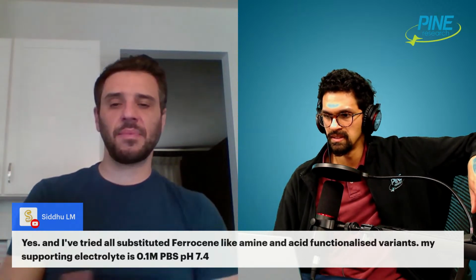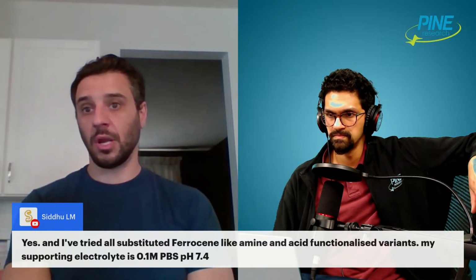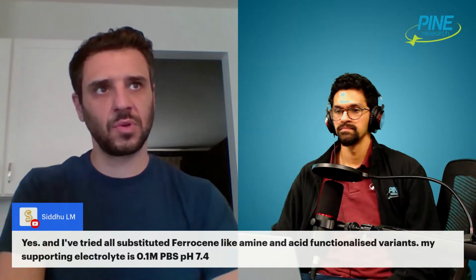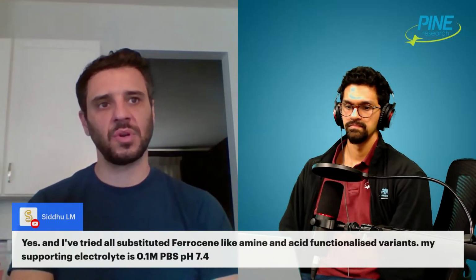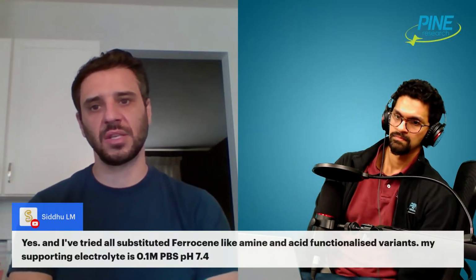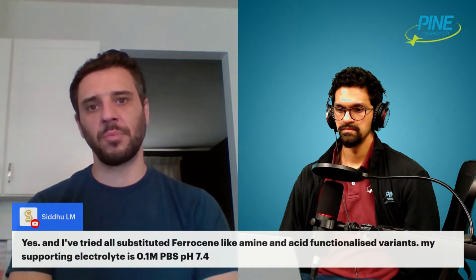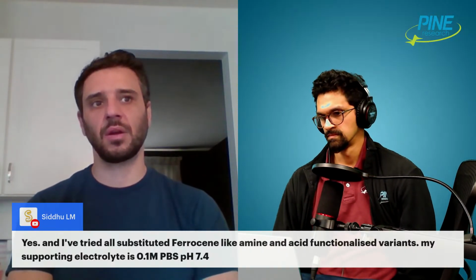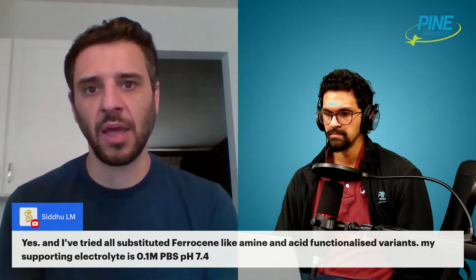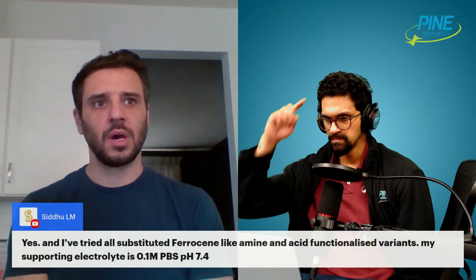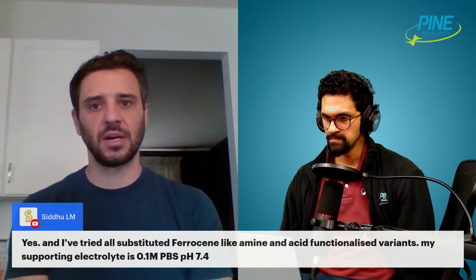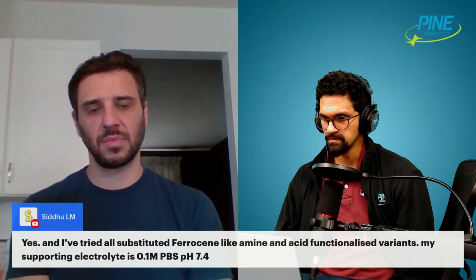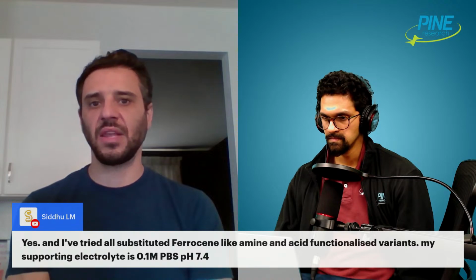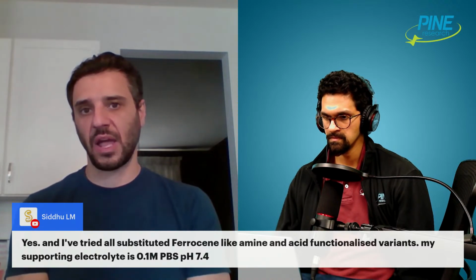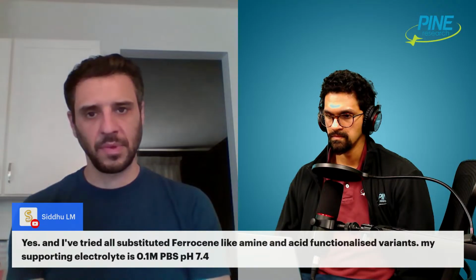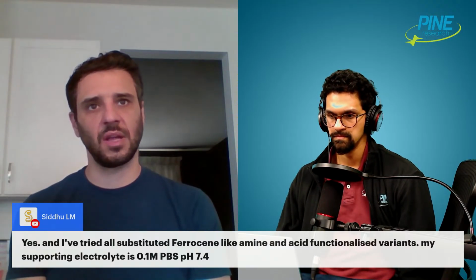And then check for the same thing. If you switch to ruthenium hexamine, now, okay, great. If that's your mediator or reference point or whatever it is that you're doing, check that its current isn't also decreasing over time. That would probably be a strong indicator that there is something perhaps awry with your electrode, with the carbon nanotubes, something like that. Then you might need to still look at those things. But if you're finding that the signal for the Ruhex is just fine, unlike the ferrocene, then using ferrocene in aqueous was probably the problem.